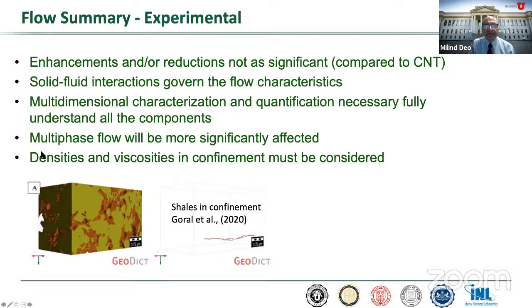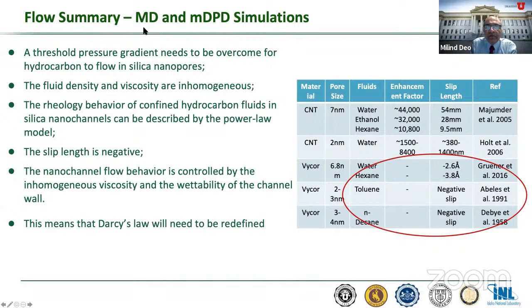I have to add a caveat here that we do need to consider the density and viscosity changes, as was shown here. The comparisons that I showed you for enhancements were all with bulk viscosities. So that's our observation there. And with both molecular dynamics and dissipative particle dynamics simulations, to answer that question about whether there is this level of enhancement or flow reduction, we are leaning more towards this evidence using these multiple experimental techniques and simulations that we have seen.